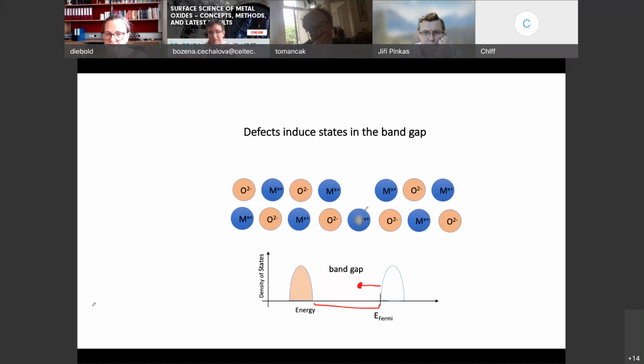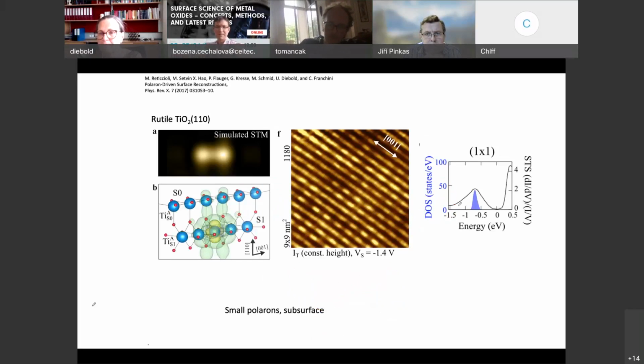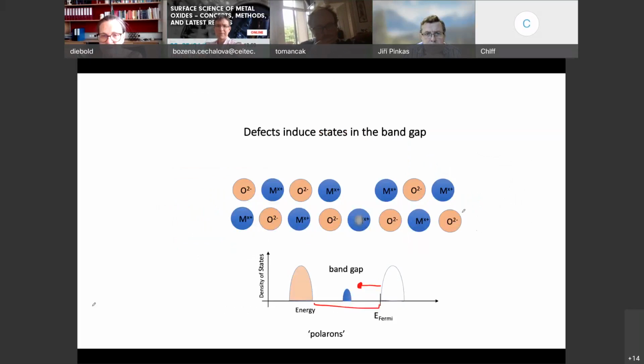And these extra electrons make this band gap state. So this state that we've seen before is because of the electrons that are left behind when an oxygen is removed. We make this oxygen vacancy and put in extra electrons. These extra electrons make this extra state in the band gap, and they're actually located in titanium atoms underneath the surface of the sample. So this is the schematic I showed you, right?